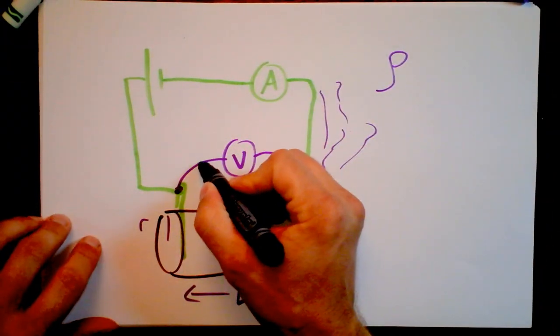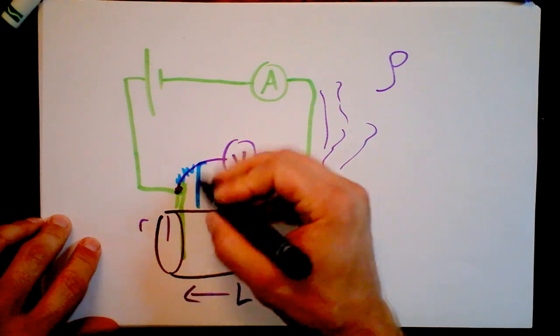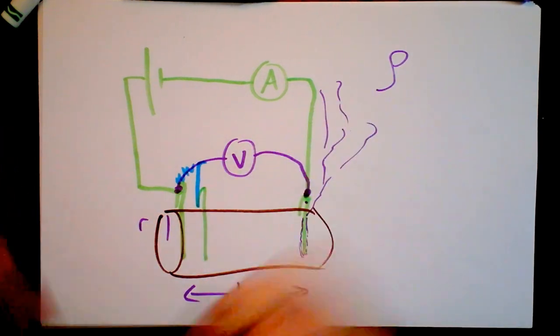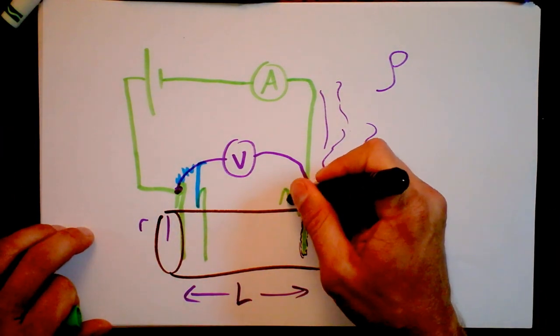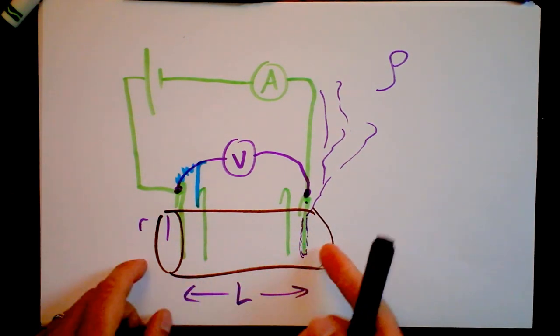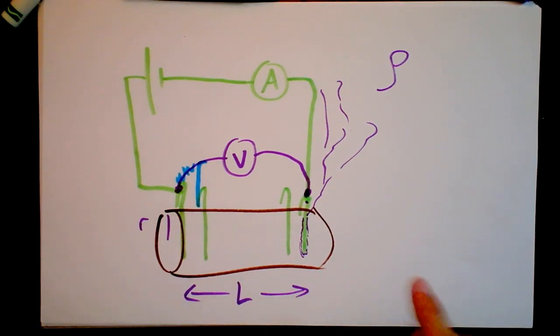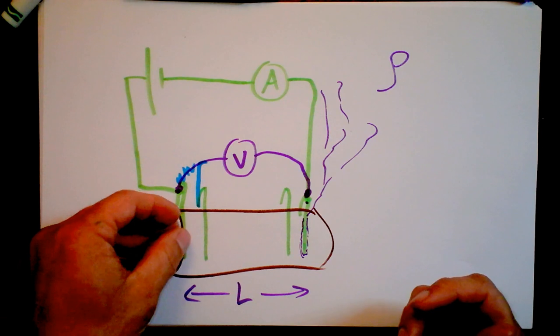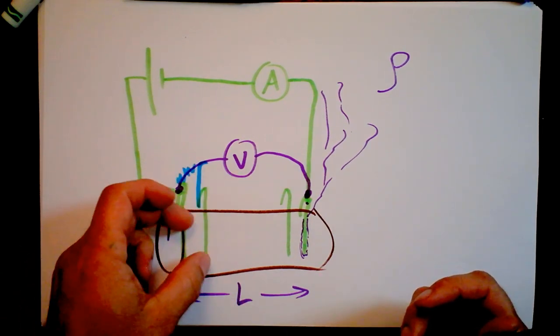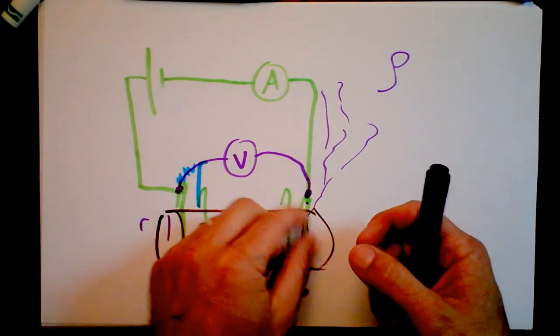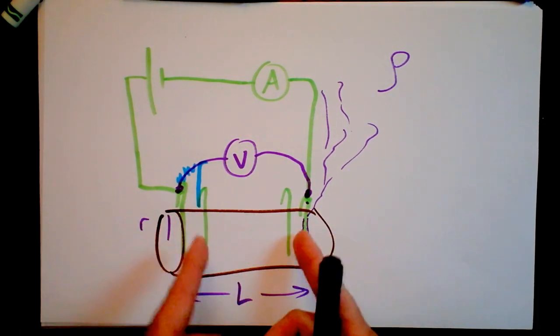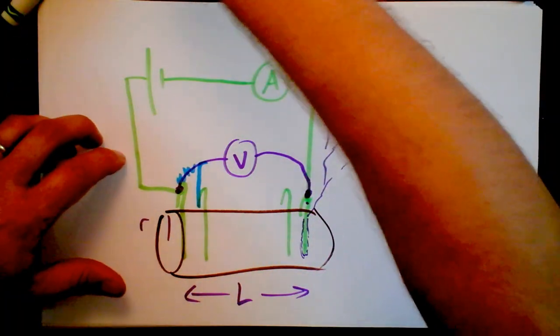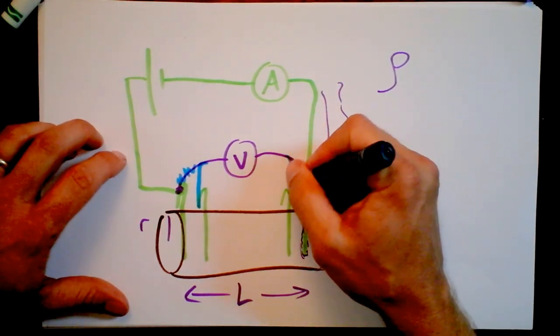You want to get the resistance of the material itself. So you say to that multimeter, come on, narrow it in a little bit. Let's never mind all this stuff. Let's go this way and go in here to our own bent paperclip. I guess in this world, paperclips are green, right? We'll just go into there and we'll go into another paperclip that we put over here. Now we want to be far enough into this squishy circuit material that we believe that the current that's going from here to here has spread out. You know, it's going to come from this point source and kind of spread out across the bulk of it and then go through here and it will narrow back down when it gets to this one. So let's choke up a little bit, but we want to be as far as possible also because we want as much resistance as we can get so that we can measure it more accurately. And then we'll do the same thing over here and not grab onto there. We'll grab onto right here.